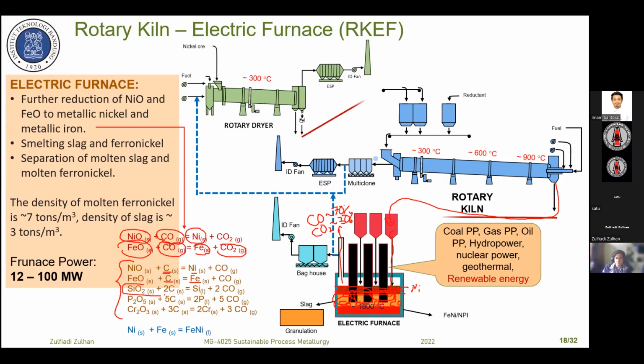Silicon oxide will be reduced by carbon, mainly around the electrode, where the temperature is high and the carbon is there, and this is also the cause of the consumption of the graphite electrode. So this graphite electrode will be consumed due to the reaction with the SiO2 in the slag. So we get silicon metal. This silicon metal will dissolve into the final product, and phosphorus also can be reduced by carbon.